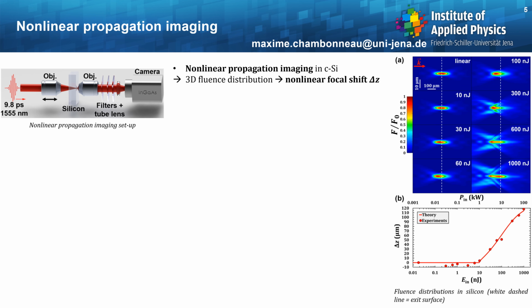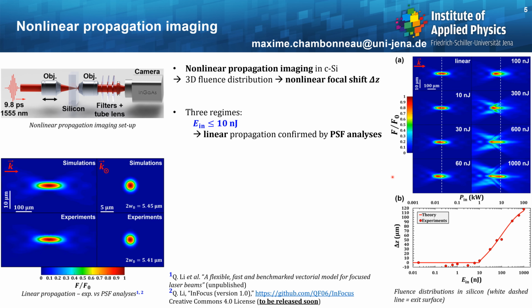We imaged the nonlinear propagation inside crystalline silicon by means of the following arrangement depicted here, which is nothing else than an inverted microscope enabling us to image the back surface of the silicon sample. And then by moving the focusing objective lens here, one can reconstruct the 3D fluence distribution inside silicon for different input pulse energies. And thus, one can access the nonlinear focal shift delta Z as a function of the input energy. On the data here, three regimes are exhibited. First, for extremely low pulse energies, lower than 10 nanojoules, the propagation is basically linear, as confirmed by point spread function analysis that we carried out thanks to our in-house tool, which will be released soon. This is called InFocus.